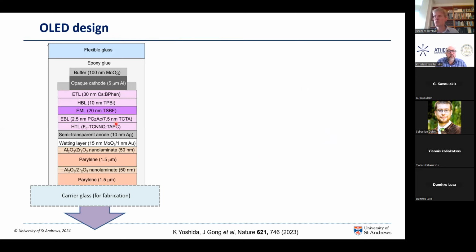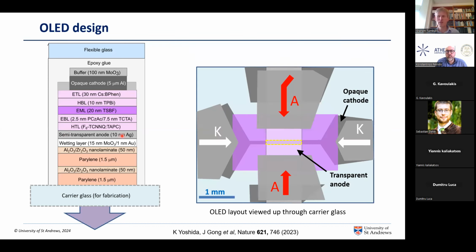This is the device stack that we finally got to after quite a lot of work on Ko's part. It shows our light emitting layer in purple between charge transport layers that are doped to be very low resistance on either side. We have a thick opaque cathode that acts as a mirror to send light always downwards through the device, and a semi-transparent anode. There's also a lot of engineering in the plane of the device: two contact wires come into the thick opaque cathode, which runs along as a long stripe in the light emitting part of the device, and then we make the thin transparent anode as short a path length as possible to make a rectangular shape that will generate the electroluminescence.